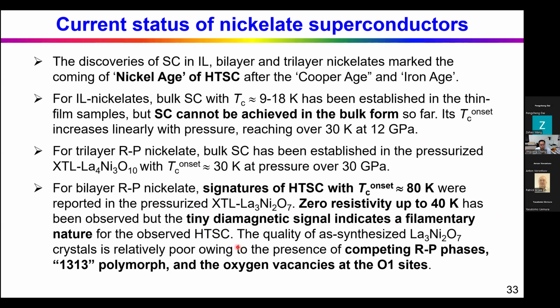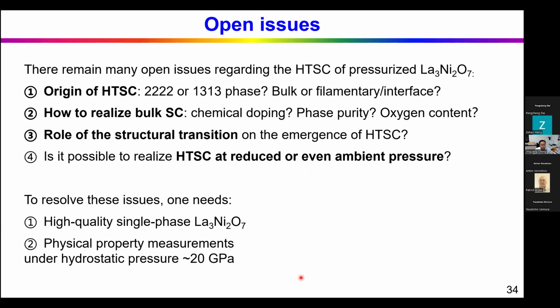So the main problem is that the quality of the single crystal is still relatively poor at this moment because of the presence of competing Ruddlesden-Popper phases, maybe some 1313 phases, and also oxygen vacancies. So there are many open issues regarding the high TC superconductivity for the 3-7 phase. One is the origin of the high TC superconductivity, and whether it's from the bilayer phase or from the 1313 phase. Is it bulk or filamentary or from the interface?